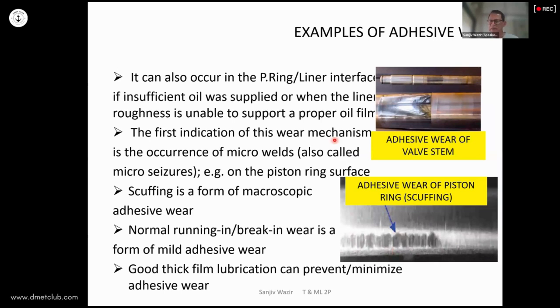Some examples of adhesive wear typically taking place in areas where the film is lost, right? For example, the valve stem is a difficult place to lubricate, and it is commonly known to have adhesive wear taking place on the valve stem, etc. The normal running-in that we have in the initial stages of our machinery is also a kind of adhesive wear, but it is actually a useful form of wear in the sense that in that period, the excess surface roughnesses left behind by the machining process are being polished off, so that you end up with a surface which will last for the rest of the life of that machinery. But sometimes the oil film is lost, or the surface roughness is so high that contact does take place. And when that excessive contact takes place, we know it by a term called scuffing, which is a very extreme form of adhesive wear, right? So as I said, a good thick oil film is the mechanism that we normally use to prevent adhesive wear from taking place.